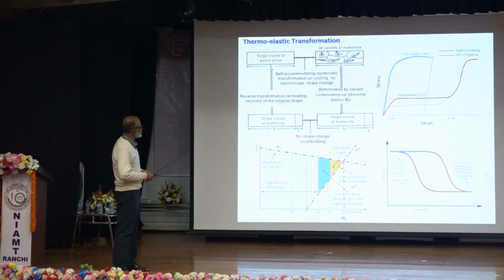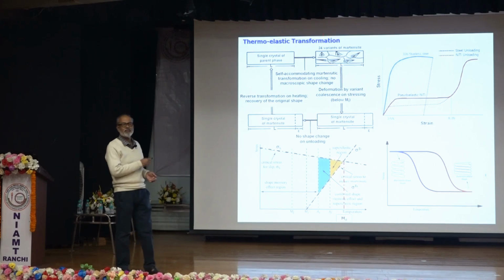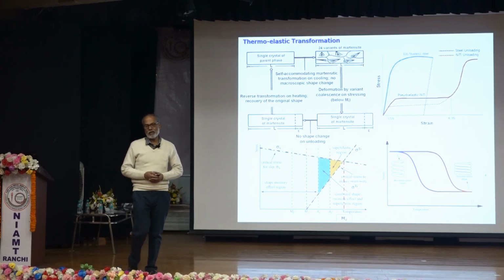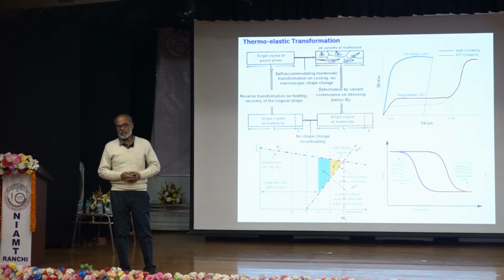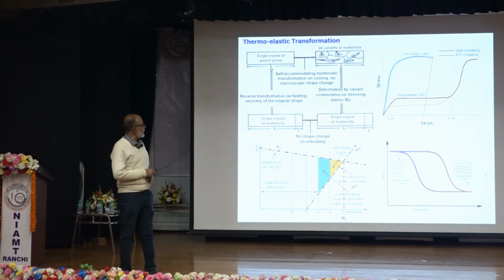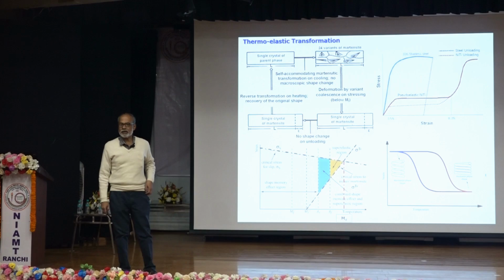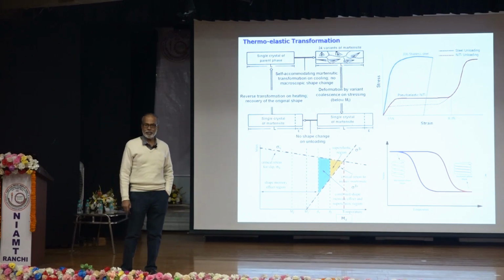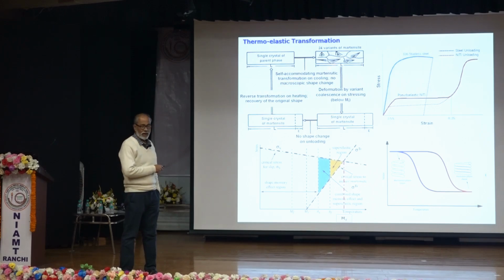Now, once it is a single crystal, when you withdraw the load, there is no change. But as it is a single crystal, when you heat it up, it will go back to the original austenite grain from which it was formed. It will retain the shape, size, everything of the original austenite grain. So we can say the martensite can memorize the austenite. That's why it is called shape memory alloy. If you combine all the austenite grains together, the same thing.